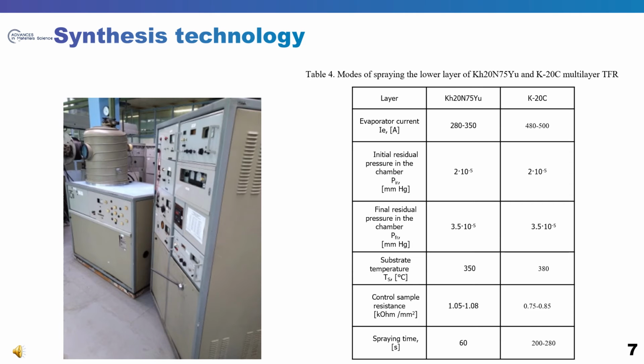For highly stable heaters with temperature self-compensation due to the proposed two-layer structure, two main problems are solved in the process of developing the technology. At the first stage of the technology development, a variant of the multilayer thin film material was determined, which will be the lower layer of the formed structure. At the second stage, the technological modes of stabilization and adjustment of the thin film were determined by high temperature impacts in vacuum and air. Material with a positive TCR sign was sprayed first. Therefore, the lower thin film layer was nichrome.